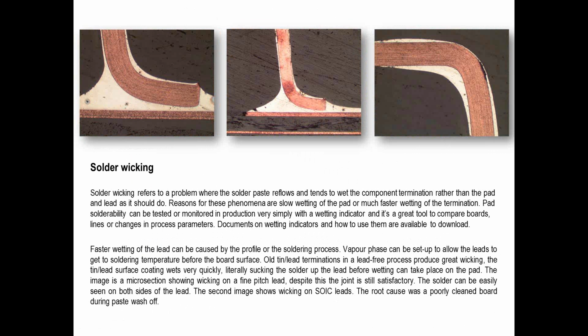You can also get this same phenomenon take place if you're soldering, which you really shouldn't be now, tin lead parts. If you were running a lead-free process and you're running lead-free paste and reflowing, of course the tin lead leads are going to reflow first, so a quantity of the solder is going to tend to wet to those pins prior to anything else on the printed circuit board. It's fairly uncommon to find tin lead parts today. The majority of all parts that are supplied and plated are tin, and that's the vast majority of the industry and what we see. But again, wicking can be an issue.